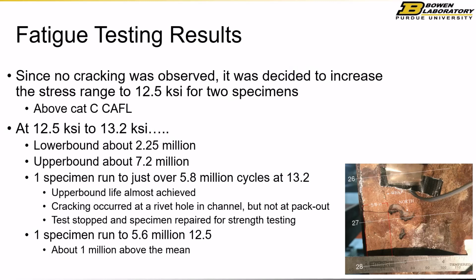We ran these up pretty high in terms of life. We didn't take them all to upper bound because they already had a lot of damage on them. And nothing happened again. The only cracking we saw was on a side plate. If you remember, they were channels, and there were some rivets for batten plates on the side vertical leg of the channel. A couple of those started to crack. So that was good news, right?